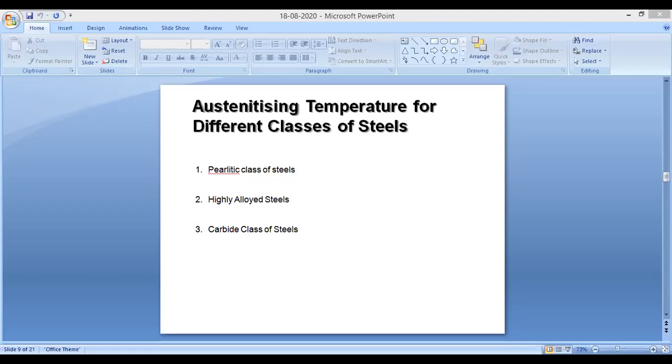Next, about the carbide class of steels. These steels are mostly alloy tool steels such as high-speed steel, having tungsten 18%, chromium 4%, and 1% vanadium. Such a steel bases its high hardness on secondary hardness, in which the magnitude of increased hardness depends on the fine and uniform dispersion of as much of alloy carbides as possible to block the motion of dislocations.